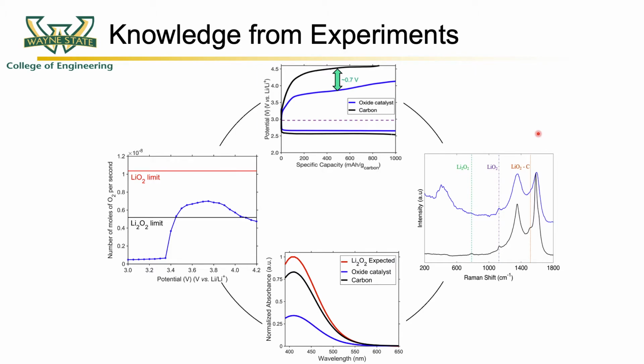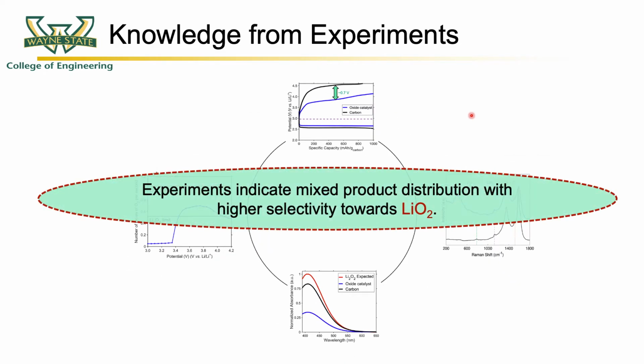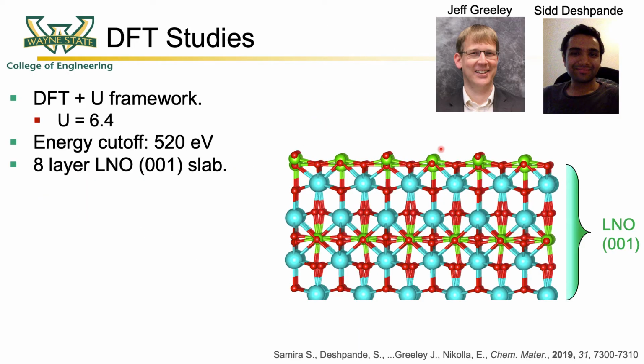These experimental studies have so far suggested that the reduction in the charge overpotentials on the rod-shaped oxide electrocatalyst is due to the selective formation of LiO2 during discharge, which oxidizes at a lower overpotential as compared to Li2O2.